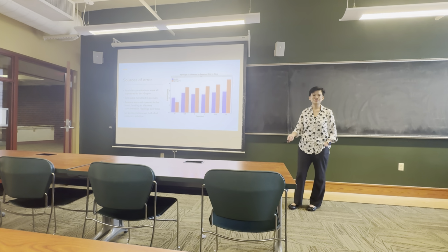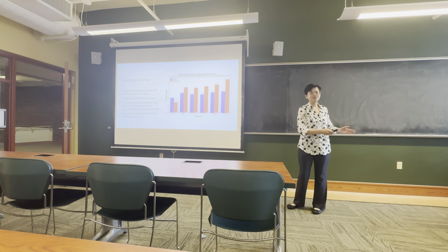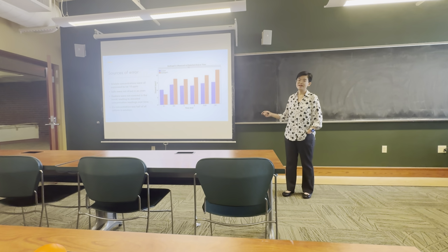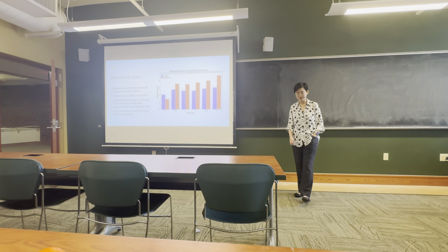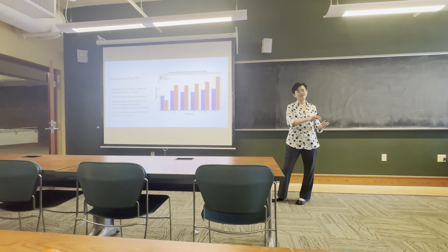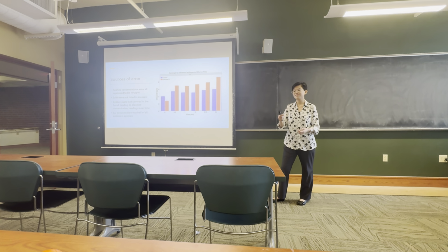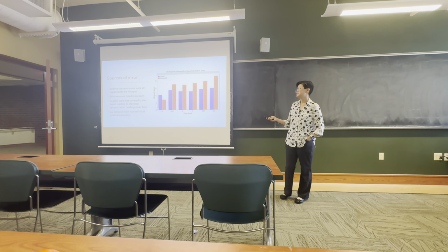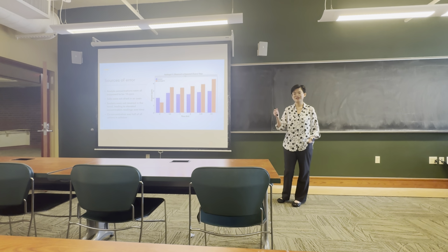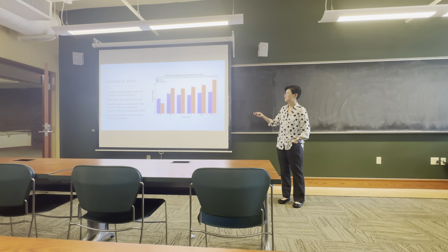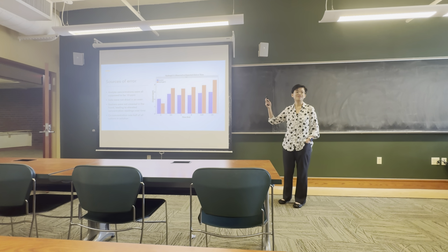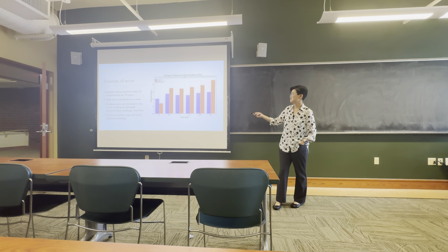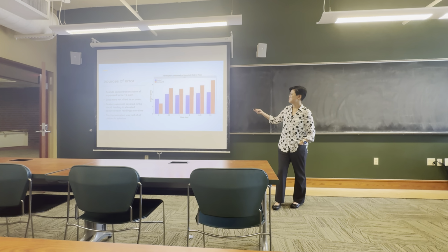Okay, so in terms of sources of error, there were a couple different areas where there could have been error, or there were errors. All the analyte concentrations were actually supposed to be 10 ppm, so I wanted a 10 ppm spike solution with 10 ppm calcium, copper, magnesium, whatever. And the salts that I used to make my standards were not dry. Some of them were kind of hard actually, so the concentrations that I calculated were different from what they were supposed to be. And also the beakers weren't covered in the hood, and you can see how this concentration increases when it's not supposed to.